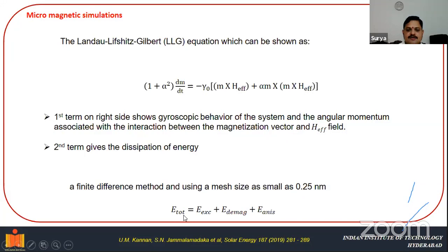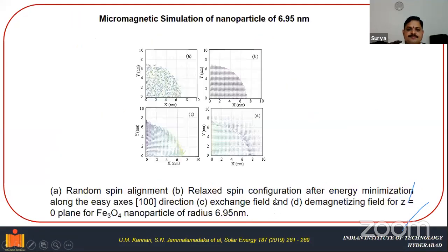And over here the E total, the energy that we have used, is the exchange energy, demagnetization energy, and the anisotropic energy. This is the kind of micromagnetic simulations that we have obtained. Initially the magnetic moments are random, and we try to relax them, and this is the relaxed spin configuration after the energy minimization along the easy axes in the [100] direction. And this is the kind of exchange field that we have obtained, and this is the graph for the demagnetization field.